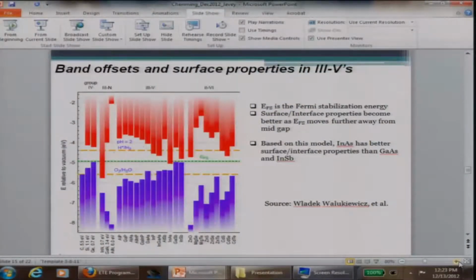But there is another important piece of information shown on this plot, which is the green line. That's EFS, which is your Fermi stabilization energy. And that's often ignored, especially by us in the device community. What this EFS tells you is that you have native oxides in any material. These native oxides, native defects, lead to electronic states. The question is, where is the position of those electronic states that you're creating by your native defects, for example, by the surface defects? If you look at indium arsenide, which is the one shown here, EFS is deep into the conduction band. That means that if you form any surface defects, the average energy associated with those defects is going to be deep in the conduction band, not in the middle of the band gap.